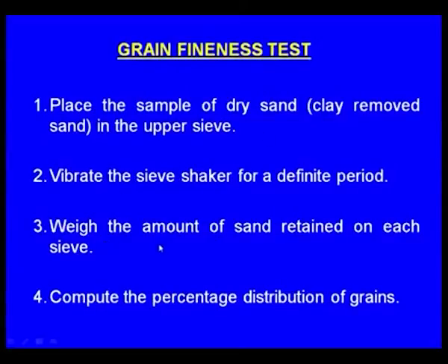Now you stop vibrating this sieve shaker and weigh the amount of sand retained on each sieve. It means we have to stop it, remove and separate all these sieves, and carefully collect the sand that is collected in each and every sieve, and we have to very precisely weigh the sand in all these pans. Then compute the percentage of distribution of the grains.